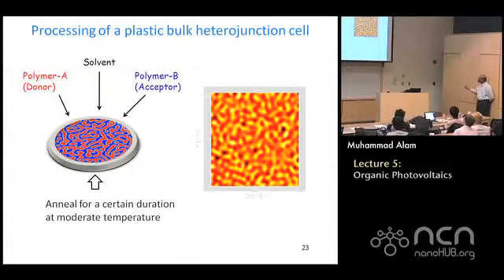In the beginning, it's completely mixed up. You cannot say which is region A, which is region B, yellow and red. If you shine a light on it, excitons will laugh at this structure because the heterojunction is not really there. Nobody is going to get separated. But after a little bit, if you anneal it, this is what's going to happen.